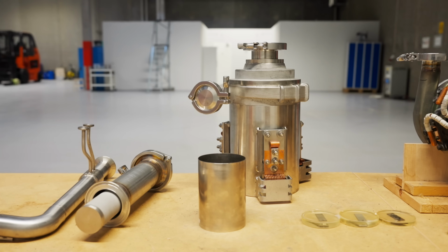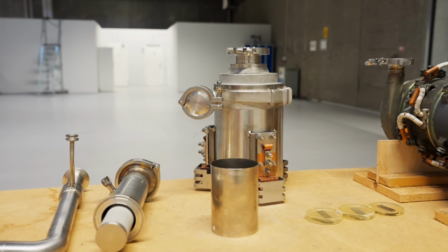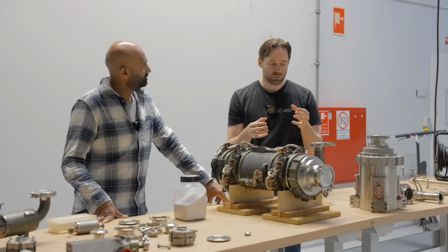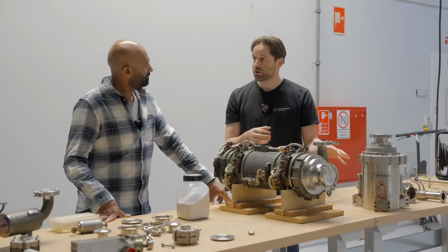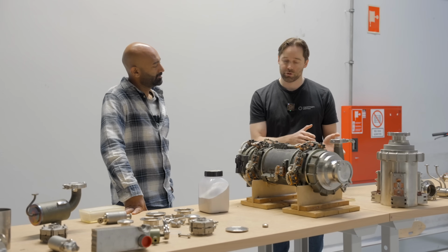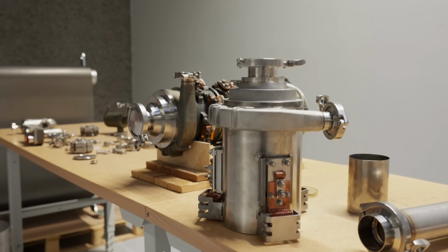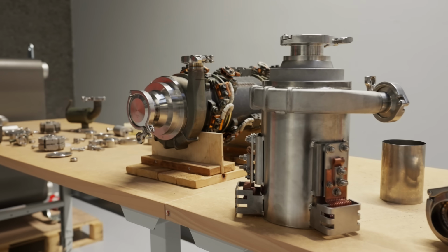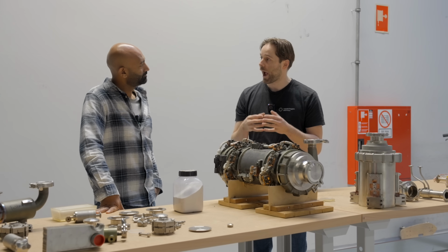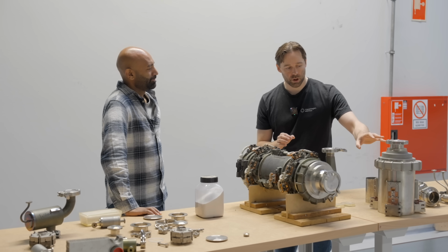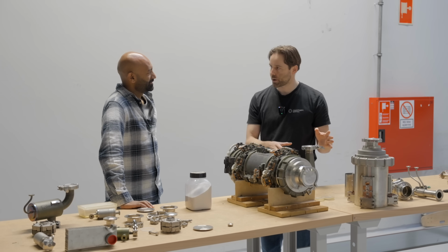We first developed this pump over here, which is a can pump, but it happens so that we cannot use permanent magnets, but we can use ferromagnetic material like iron, and we can use copper at these temperatures. It's just below the Curie temperature where iron demagnetizes, but at these temperatures it still works. We basically invented a way to then insulate the windings and use low voltage and high currents. And then the other part of this pump is that it uses hydrodynamic bearings.